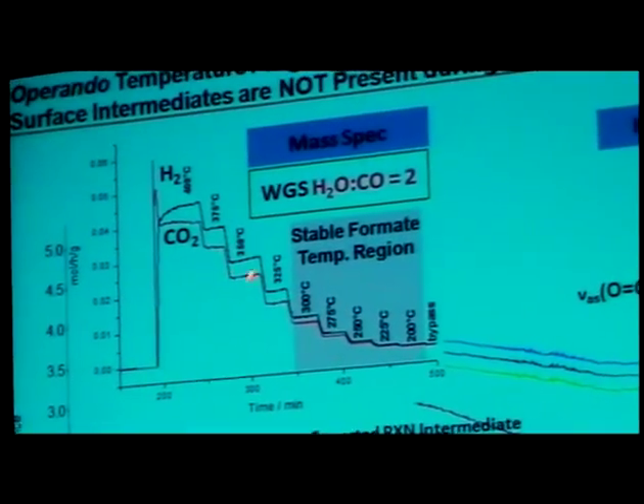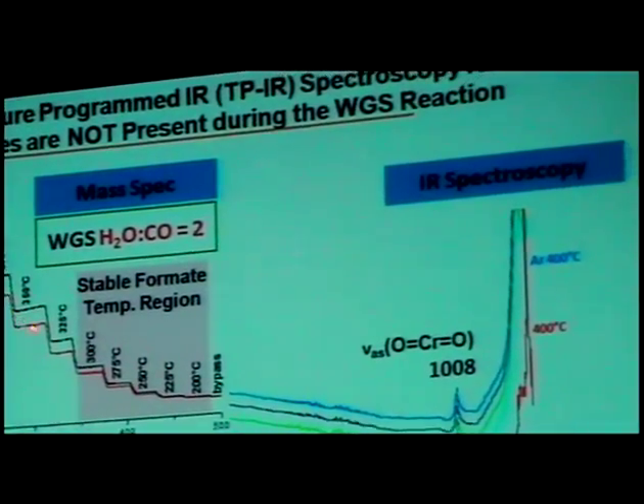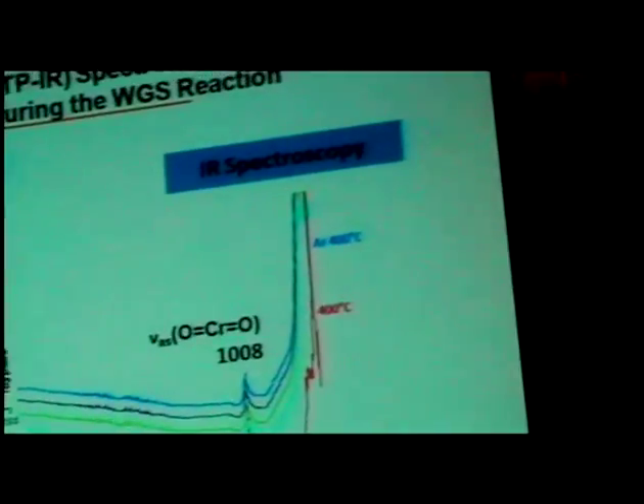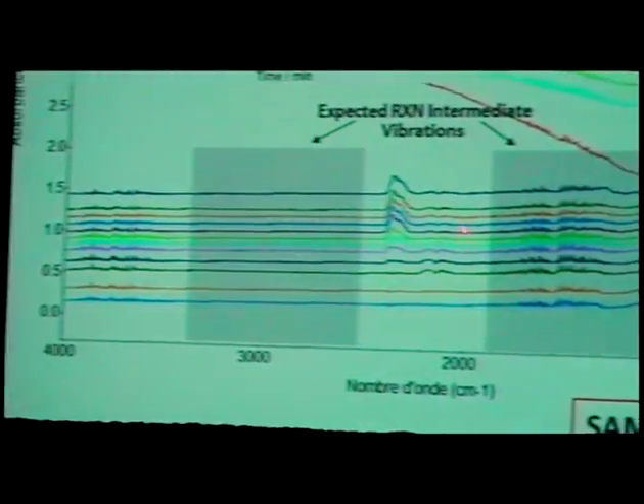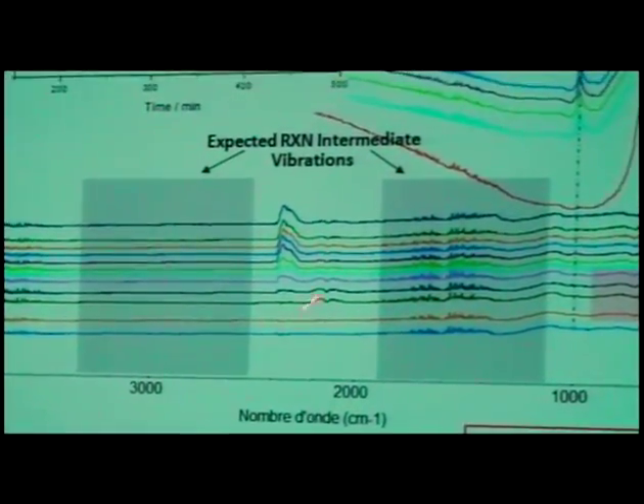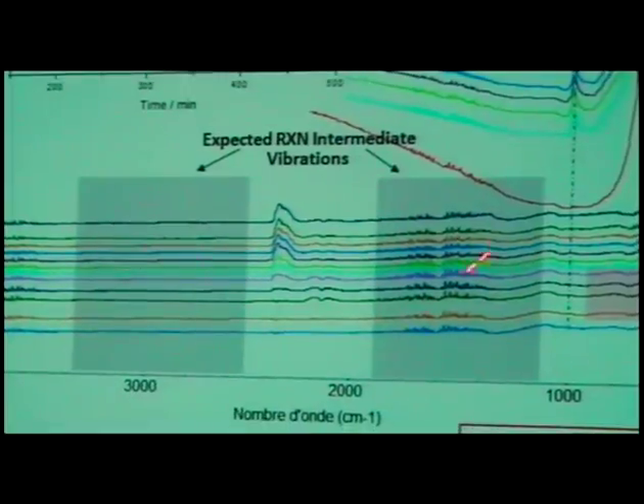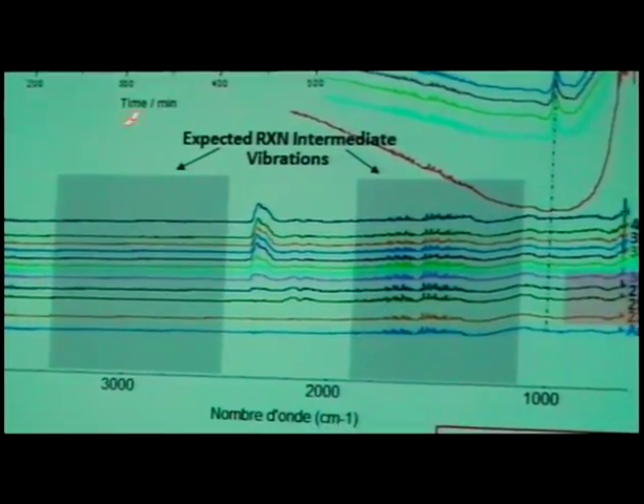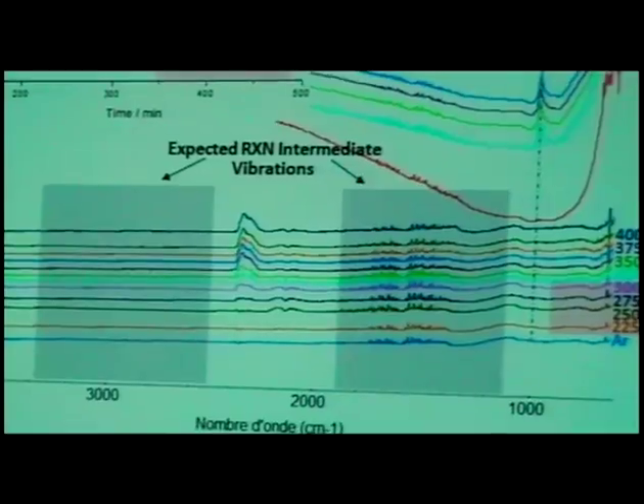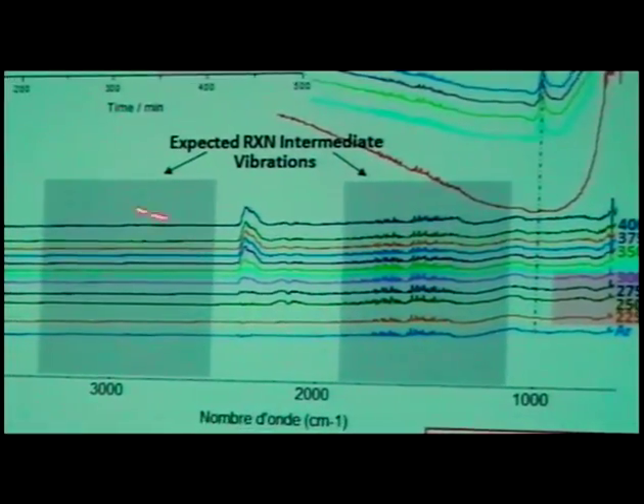So we start the reaction, and do these steps as we're lowering the temperature. We went all the way down from 400 degrees C, we started, and we lowered it down to 200 C. And while we're decreasing the temperature, here is the IR spectrum. And this is gas phase CO2. The point to make here is that formate has never been measured, even though it has been invoked consistently for decades as the intermediate. It is just not present.